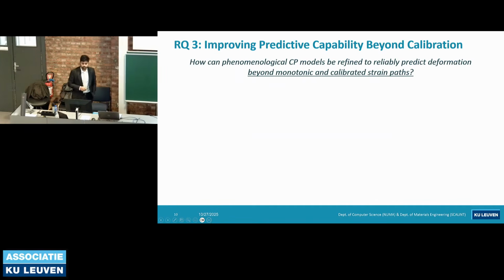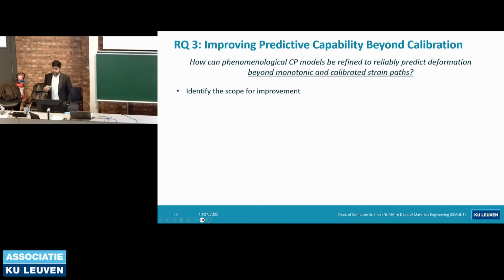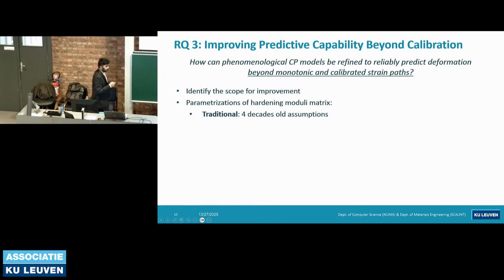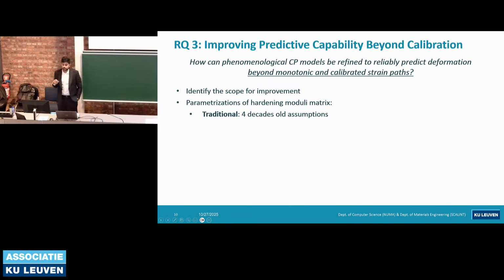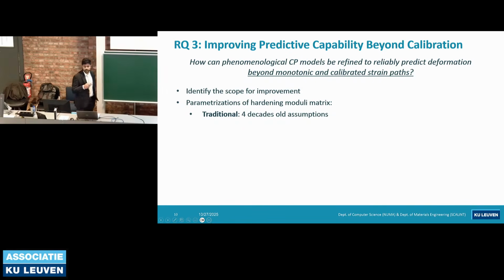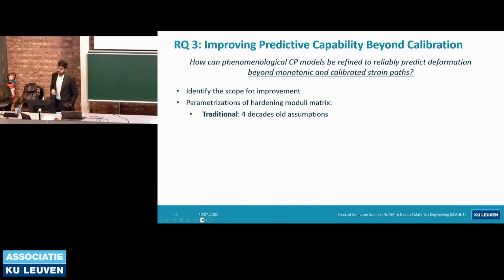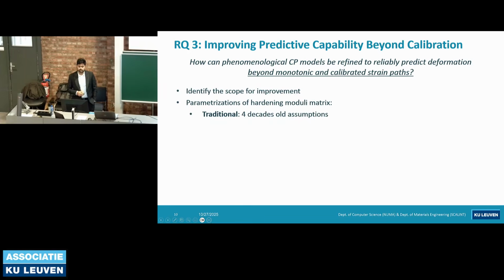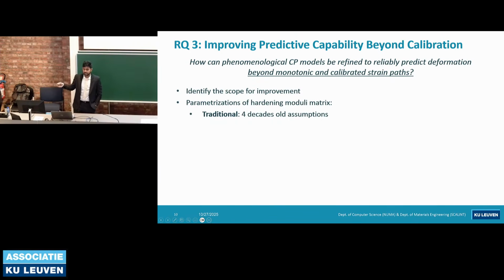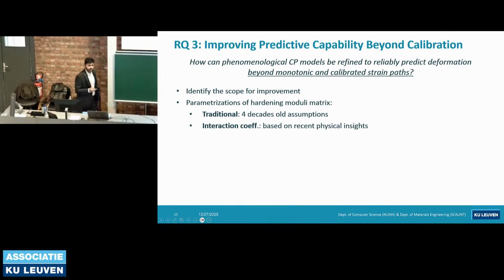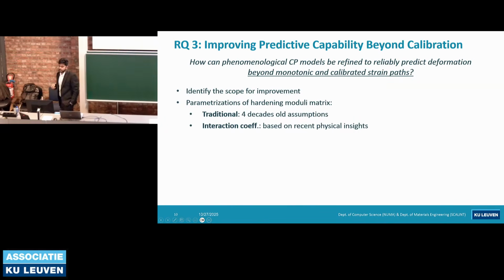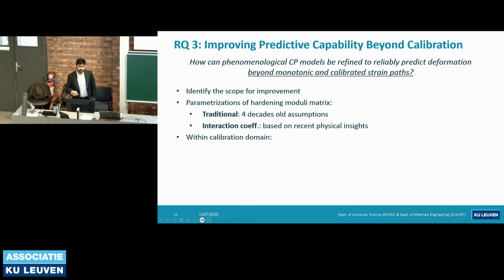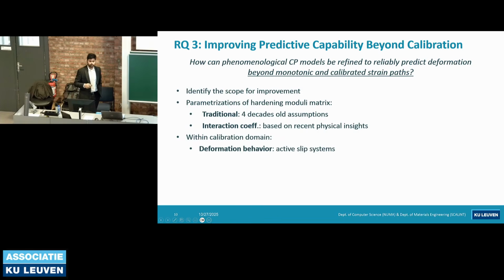So for this, the question is posed as: how can phenomenological crystal plasticity models be refined to reliably predict beyond the monotonic and calibrated strain paths? First, we identified the scope for improvement, and we noticed that for the phenomenological model, especially the hardening coefficients, 4 decade old assumptions were used and are still being used today. We referred to this as traditional parameterization. These parameterizations were based on the experimental data that was present 4 decades ago. What we propose is an interaction coefficient, which we obtained based on recent physical insights from the lower scale simulations. So the testing was done within the calibration domain first, and at two fronts.